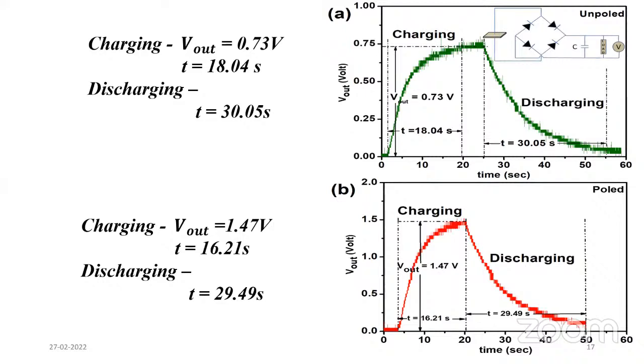At the time of charging, the output voltage was 0.73 volt and the time was 18.04 seconds, and the time it took for discharging was 30 seconds. And the other one is for the poled device, in which the output voltage was higher in comparison to the unpoled device, that is 1.47 volt in 16.21 seconds, and it took a discharging time of 29.49 seconds.